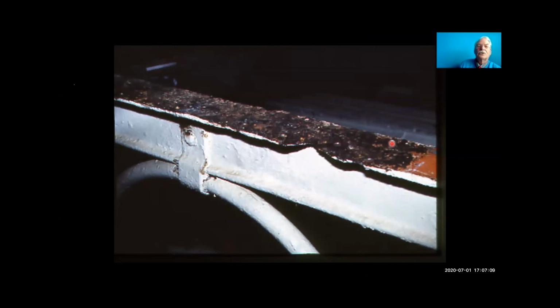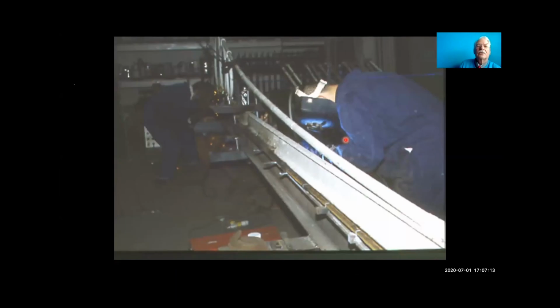It's just where the water had got underneath the repair plate. So we turned these trusses on their backs, cut off the defective plate, and welded on some recycled wrought iron with, of course, the grain running in the right direction. Very important. And you can see 2 men, one each side, welding at the same time. They're doing this because welds contract and the whole thing will bend if you don't keep it balanced.